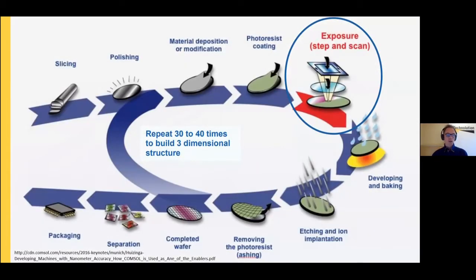The process of making chips is shown in this image. We start with a polished wafer and we go through an exposure cycle for 30 to 40 times and finally we separate and package the chips. In the exposure cycle, a layer of material is deposited on the entire surface of the wafer and this layer is covered with a photoresist coating. The photoresist layer is exposed or not, which gives the definition of the chip. After developing the resist, the unwanted part of the full surface is etched away, leaving only the required features in place.